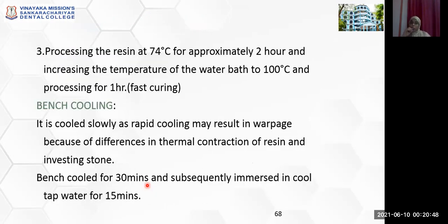Now this is the long curing cycle, whereas in the short or fast curing cycle, you use the same 74 degrees Celsius, but only for 2 hours, and then you raise it to 100 degrees Celsius and again cure it for 1 hour.